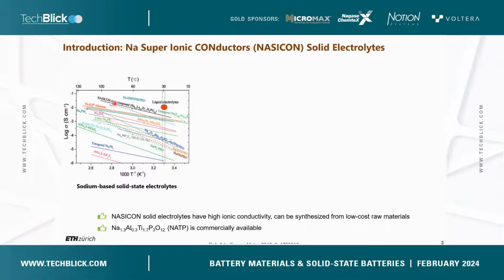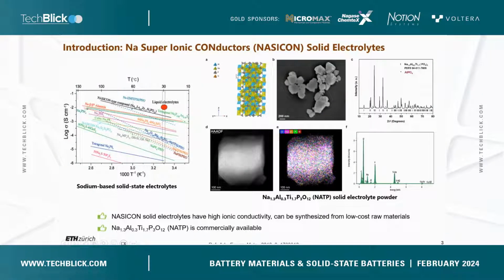The black line that you see here is the ionic conductivity variation for a NASICON solid electrolyte, namely sodium zirconium silicophosphate doped with lanthanum. As you can see, at around 60 degrees Celsius, it reaches the required ionic conductivity of a liquid electrolyte. And this is one of the biggest challenges when it comes to solid electrolyte development for both lithium as well as sodium metal batteries. The advantage of a NASICON structure is that the figure represents a sodium aluminum titanium phosphate. It's the material that I used for this present study.